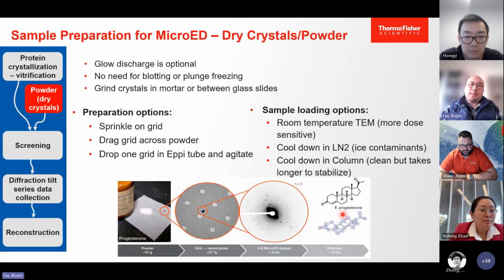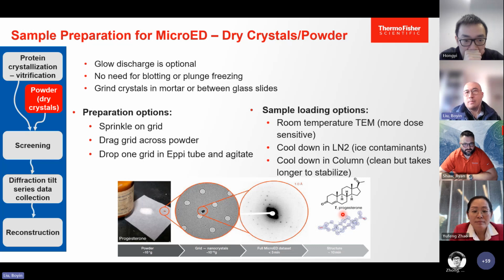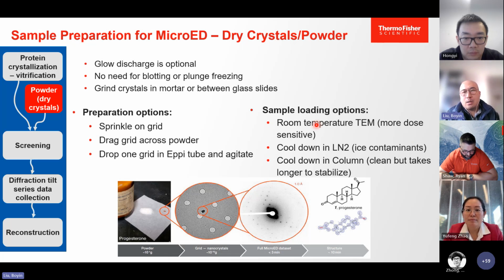That was sample prep for protein crystals, but if your sample is dry crystals or powder, preparation is much easier. Hongye has already talked about this, and I just want to stress the sample loading options here. For this kind of sample, you can actually do them at room temperature. It's just that the sample is going to be more dose sensitive because there's no cryo protection, but it works. Or you can just cool down in liquid nitrogen quickly. No need to use liquid ethane because there's not much difference there, but you need to be careful with ice contaminants in the liquid nitrogen, especially when your crystal looks very similar to ice crystals.